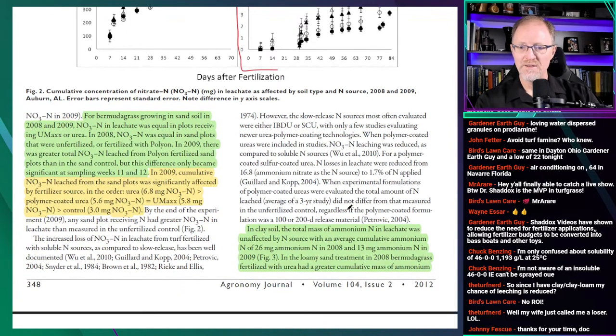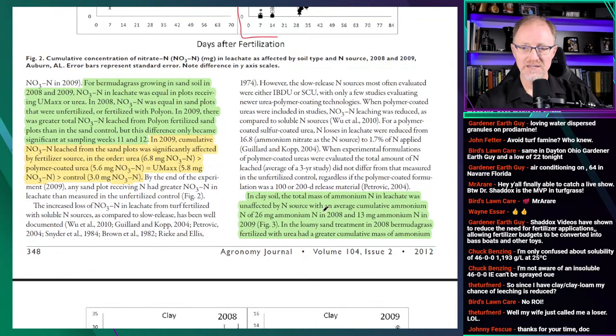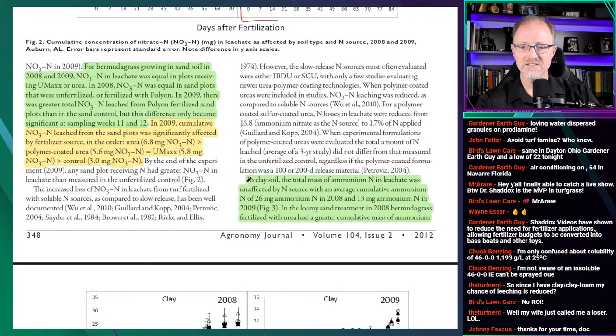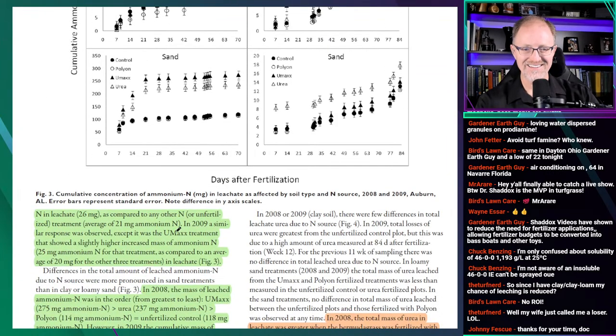Okay. In clay soil, the total mass of ammonium in leachate was unaffected by nitrogen source, with an average cumulative ammonium nitrogen of 26 milligrams in 2008 and 13 milligrams in 2009. In the loamy sand treatment in 2008, Bermuda grass fertilized with urea had a greater cumulative mass of ammonium in leachate as compared to any other nitrogen or the unfertilized treatment, an average of 21 milligrams of nitrogen. In 2009, a similar response was observed, except it was the UMaxx treatment that showed a slightly higher increase in mass of ammonium nitrogen in leachate.